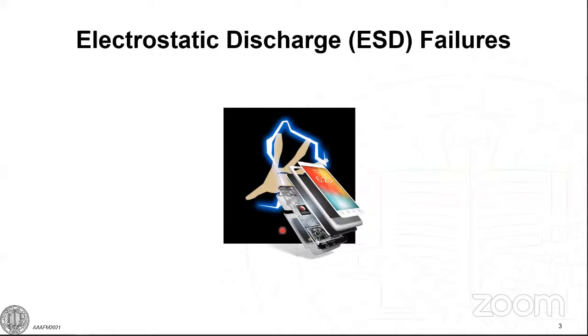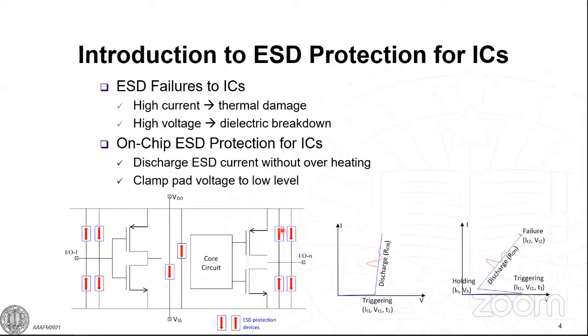The only reason that we can use a smartphone without worrying too much is because we have some kind of protection measures in place, and this is something I want to discuss today. So what about ESD and ESD protection? As I mentioned, the electrostatic charge inside the human body can discharge into any electronic device. It will generate a huge current pulse, on the level of 2 amps, and that generates a lot of heat inside the integrated circuit and the electronic equipment, and that may cause thermal damage. Another phenomenon is a huge voltage spike that will generate a transient very high electric field density, and that will create some dielectric breakdown. Those are the problems we have to worry about.